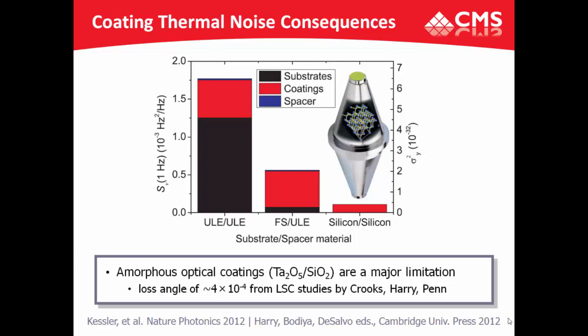And just to give you numbers, the mechanical loss angle, which is the inverse of that quality factor Q that we discussed before, is at the level of 4 times 10 to the minus 4. So we're getting a couple thousand mechanical Q for those